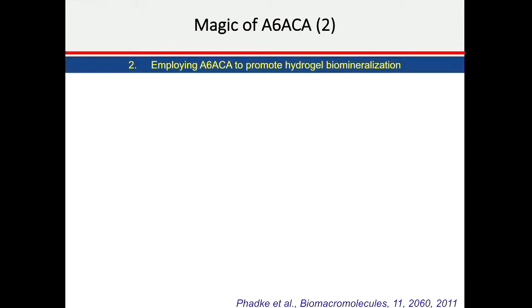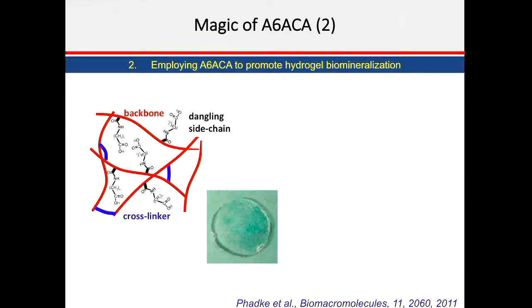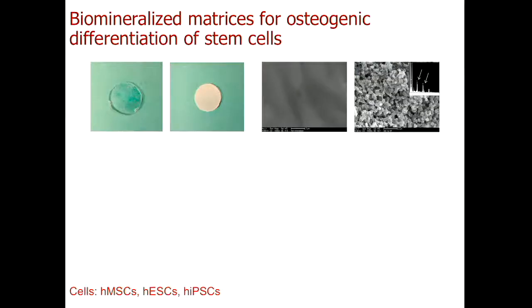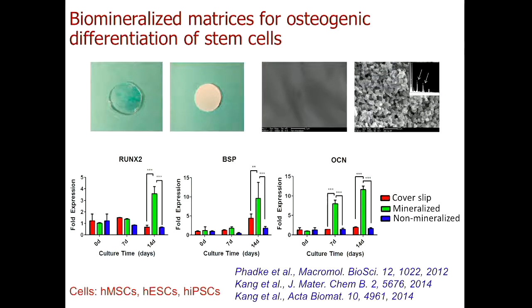The other one was this hydrogel biomineralization, the dangling side chains, and you can see the kind of biomineralization that takes place with calcium phosphate, which is very critical. And you can see, for example, the fold expression. If you look at the mineralized one versus the non-mineralized, non-mineralized is blue, and mineralized is green with A6-ACA. You can see the maximum with the mineralized one.